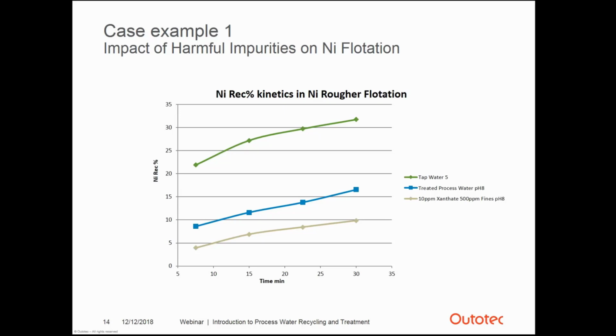Well, naturally, tap water gave the best results, the green curve in the graph, but this graph just illustrates how water quality has an impact on the flotation recovery. And with a relatively simple water treatment, we achieved a significant recovery increase compared to the process water without any treatment.